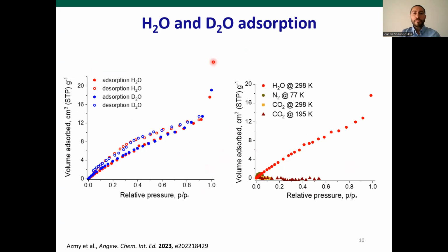To validate the porosity, we performed gas sorption studies using water, deuterium oxide, nitrogen, and carbon dioxide gas molecules. Apparently, the material can selectively absorb and desorb reversibly water and deuterium oxide at room temperature, but it's impervious to nitrogen and carbon dioxide. This means that the material is ultramicroporous, and based on the X-ray diffraction studies, the cavity of the DHS linker is estimated to be around 4 angstrom without taking the van der Waals radius into account. So with this into account, the cavity would be less than 2 angstrom.